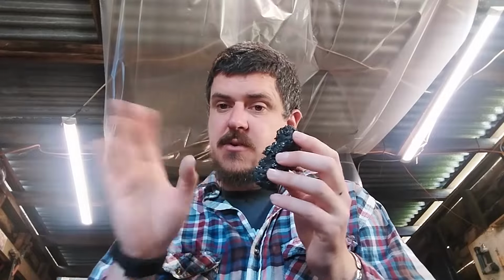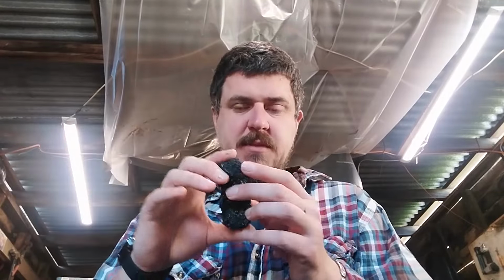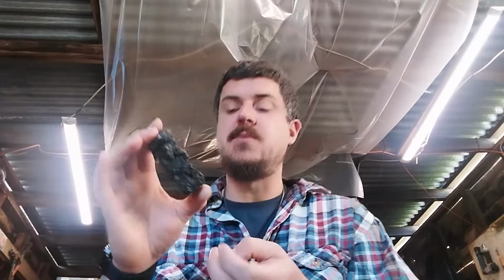As it releases those gases and as the liquid slag comes off, that's going to potentially spray everywhere, although with one this small, we'll be doing smaller hits, which is good. If you have a big bloom, you see huge amounts of sparks and slag fly off of them because they have to do quite big hits to get the impact needed to actually consolidate them in the middle. Whereas working a little hobby-sized one like this is not much work. You don't have to hit very hard for the penetration to go all the way through.